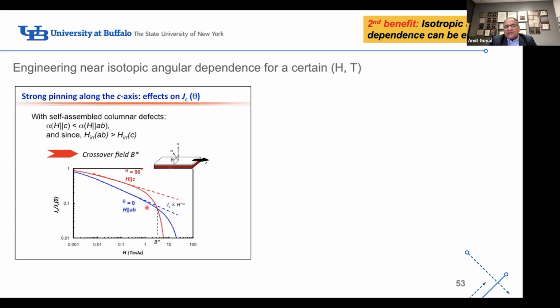H parallel to AB is when the field is applied parallel to the superconducting planes in the unit cell. There you get very high intrinsic performance. And when you create this nanostructural modification, we actually get a higher performance than that, even because of that nanostructural modification. But at higher fields, it crosses over and becomes lower. So it crosses over at this point.